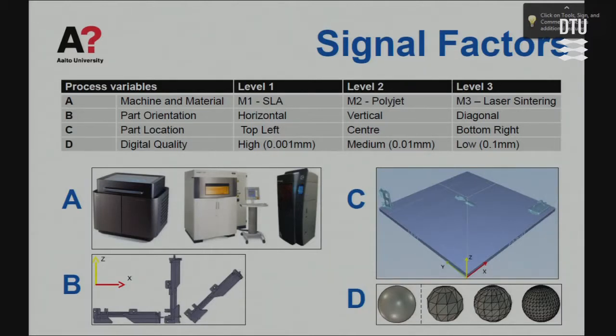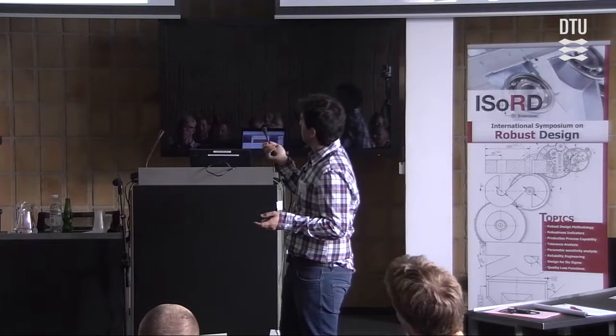And the last signal factor I used was the quality of the STL file. So this is the nominal value, and depending on the quality you get, you get this geometry. This is measured with the chordal error, which is the shortest distance from the nominal value to the facet. So it's the high quality 0.001, 0.01, and 0.1. So I started with this, and then we wanted to measure.